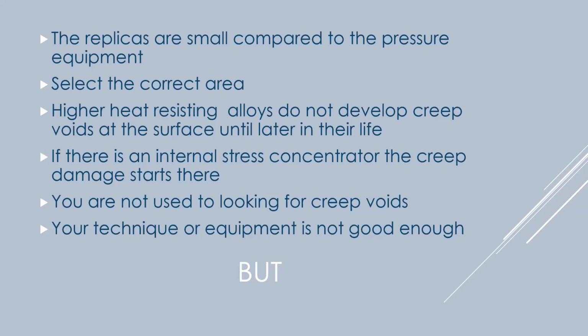So that means that somebody has to be able to give you information where things have failed in the past, maybe where they found high temperatures, maybe they did a finite element analysis and determined that this was a more applicable area. The other problem with doing these in situ replicas for creep is that these higher heat resisting alloys like the 9% chromium don't develop creep voids at the surface until later on in their life. So the method that we just talked about doesn't work for them.